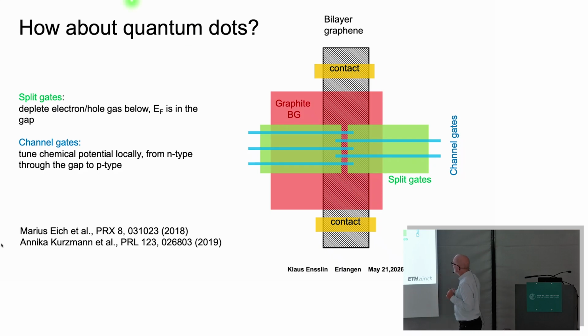So this is the schematic of how we build a device. I left out all the insulating layers. These are just the conducting ones. So there's a graphite backgate. Then this is our piece of bilayer graphene. Then you see the green gates. The green gates we call the split gates. And now when we apply appropriate voltages between the split gates and the backgate, then these regions here are insulating in bilayer graphene, and the current between the contacts has to flow through this narrow channel.